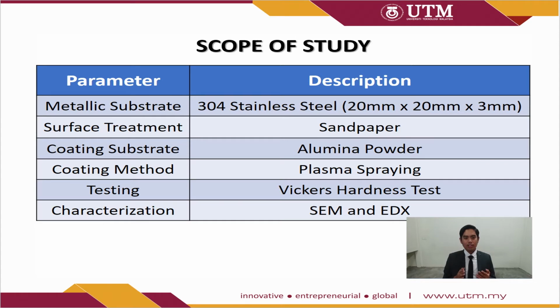Then the scope of study is summarized in the table as shown. Firstly, the metallic substrate is 304 stainless steel, which has a dimension of 20 mm length, 20 mm width and 3 mm thickness. Next, the surface treatment used is sandpaper, and the coating material used is alumina powder. Then the coating method is plasma spraying, and lastly, the testing is conducted via Vickers hardness test, and characterization is being done by using SEM and EDX.